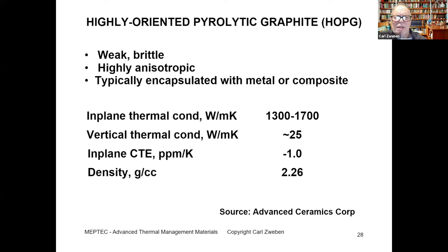At the upper end of the spectrum of carbonaceous materials, we have highly oriented pyrolytic graphite, which has thermal conductivities as high as 1700 watts per meter Kelvin in the in-plane direction, and in the through thickness direction much lower, about 25. And again, negative in-plane CTEs and densities that are higher than the flexible graphite, but still lower than aluminum.